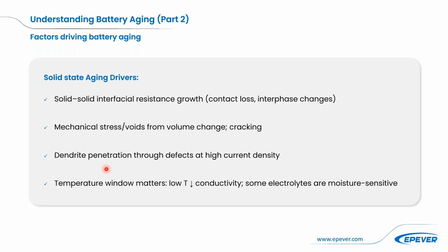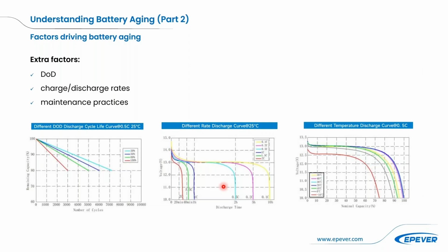So in short, we need to manage the state of charge. The DoD is important, but more depth of discharge means a lower life cycle. Temperature, we need to control it. And we need to also choose the settings that suit the chemistry that we are applying. You see, the aging mechanism is different for lead acid, for lithium, for solid state. So the charging settings must be set up carefully for that specific type of battery. And again, that's where we have the BMS, the battery management system, and good commissioning that are the critical points for higher life cycles.